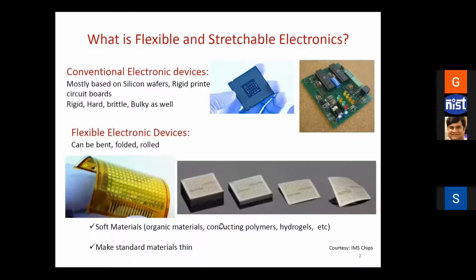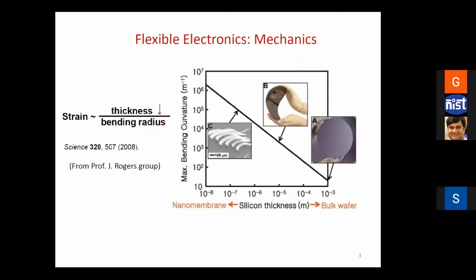Another way that people have tried to work on is using soft materials, for example, organic materials, conducting polymers, hydrogels, etc. And another approach, as I said, is to use the same silicon-based materials and make them thinner so that they become flexible. If you see the mechanics of it, why thickness plays an important role, it goes by this simple expression: strain is related to thickness divided by bending radius. That means if you reduce the thickness, then for a particular bending radius, it will be able to accommodate more strain, right?